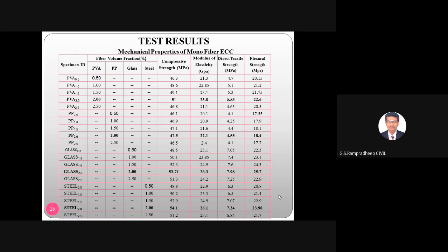Second to 5th column, and the corresponding compressive strength, E value, direct tensile strength as per the dog-bone specimen, and flexural strength as per 2-point loading, as per Indian conditions. The maximum strength is marked in bold. For example, PVA at 2% volume fraction, your maximum compressive strength is 51 MPa, and correspondingly the E value, direct tensile strength and flexural strength. In our IS code, the FT value you calculate is 0.7 root FCK, right? And similarly, you need to balance with respect to the compressive strength for the different types of strength, like tensile strength and flexural strength, etc.